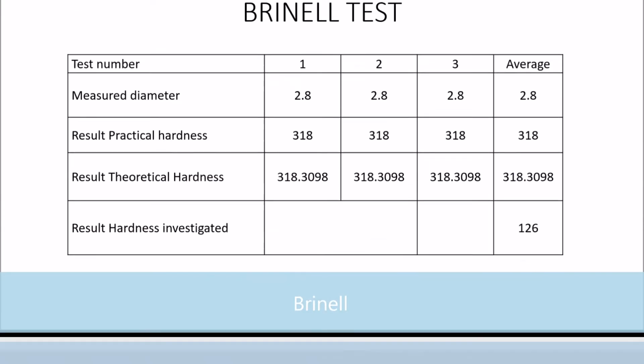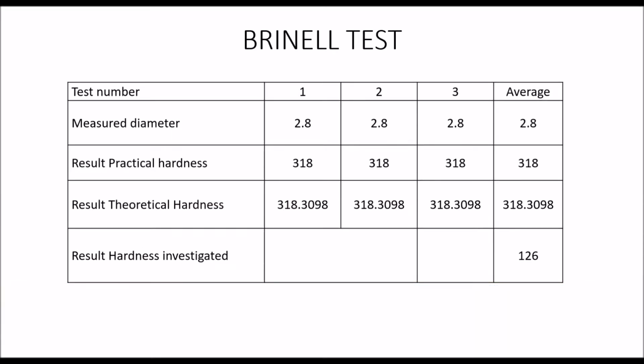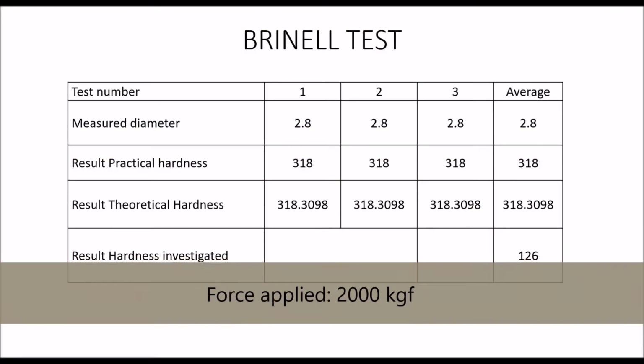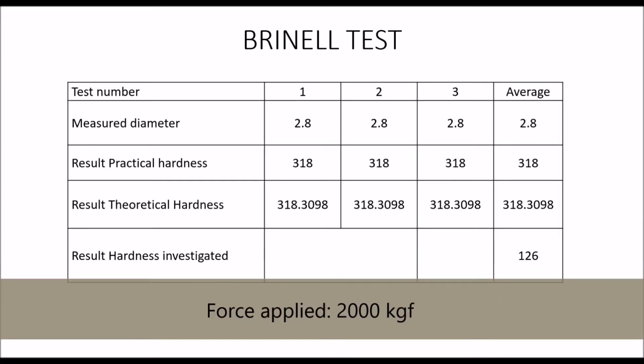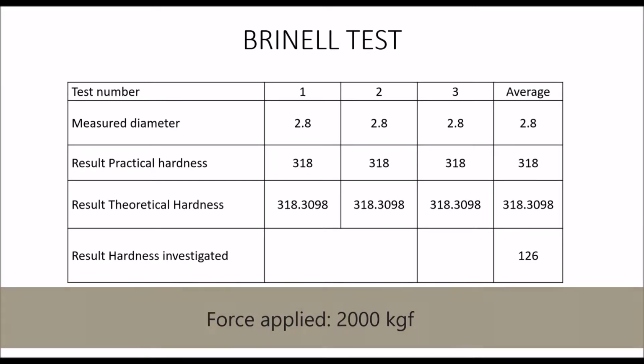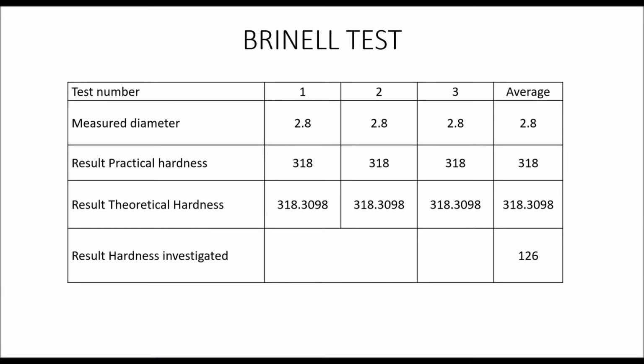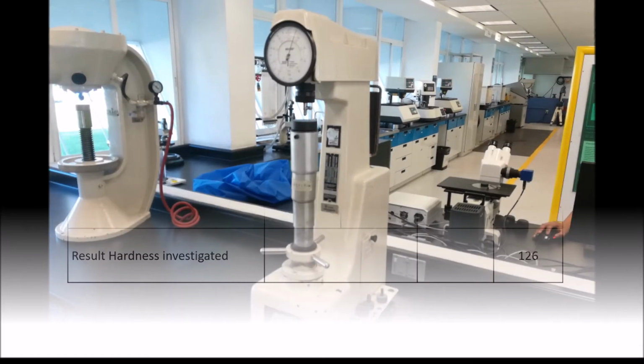Now we have the hardness test. The first hardness test that we made in this practice was the Brinell test. We have 3 samples. All 3 had the same measure of diameter and the same average, so the result in practical hardness was 318 in all 3 of them. Then I calculated the theoretical hardness, and it was 318.3098, and the one that I investigated was 126.